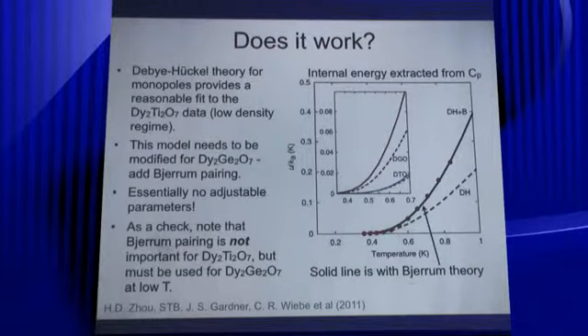And there are really no adjustable parameters within this theory. You're using parameters you've already defined. Right? So you have to use the Debye-Hückel plus this Bjerrum theory in order to fit this data properly at low temperatures. And it's not even really a fit. You're just taking the parameters that we extracted before. So if you're really looking for monopoles, there's a high density here, and this sort of pairing effect is noticeable and measurable at low temperatures.